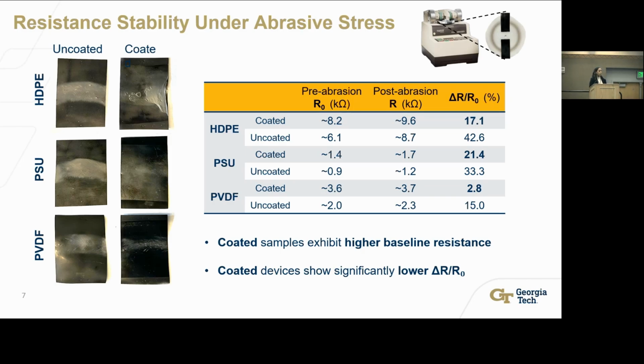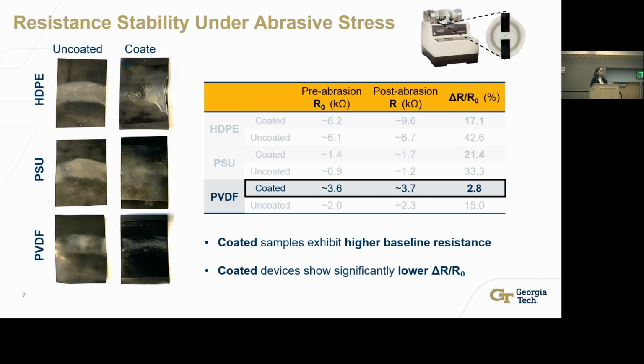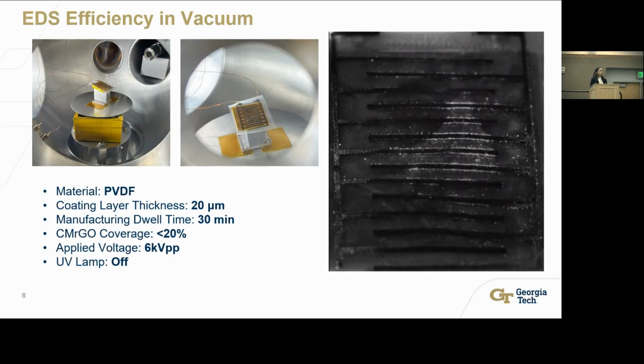So what one can deduce from this chart is that the coated samples initially exhibit higher baseline resistances, and this is understandable because there is more infiltration of the polymeric dust into the dielectric matrix with an additional cap layer on. However, if we look at the farthest right column highlighted in bold, we can see that the coated devices are showing significantly lower changes, and they're actually protecting our internal circuitry against the abrasive dust. And we can see that with only 2.8%, PVDF is again standing out from all the other material groups that we've tested. And that's why we decided to focus on a PVDF sample for the EDS performance test here.